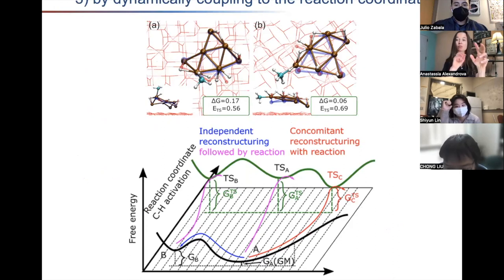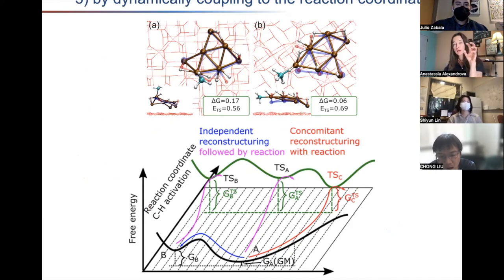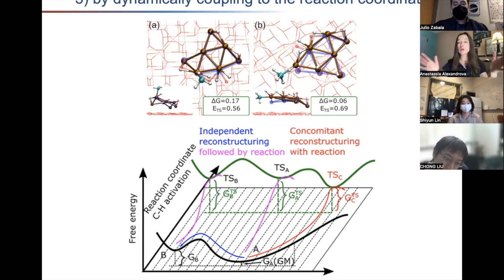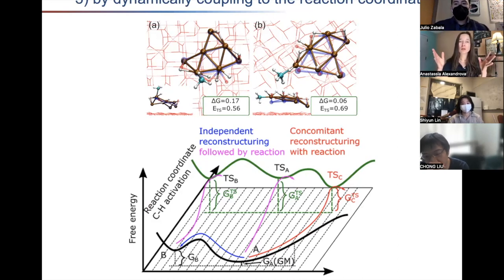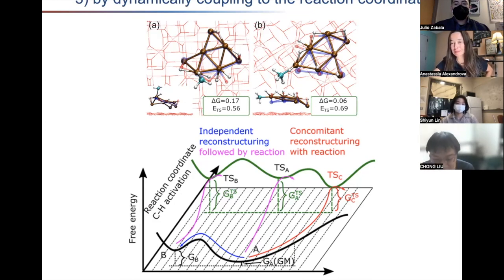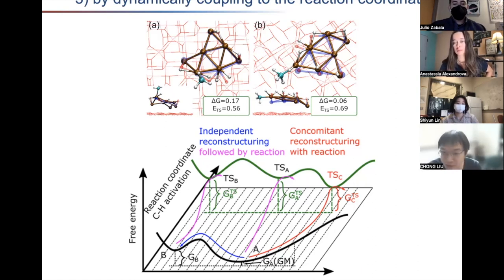We also have one paper showing that reorganization of the catalyst can be coupled to the reaction coordinate directly — meaning the reaction coordinate says not just C-H bond stretching but C-H bond stretching plus platinum is doing stuff simultaneously. That's a very difficult reaction coordinate to discover because normal NEB strategies wouldn't get you there. We fix the reaction at the transition state and sample the cluster under it, find a separate ensemble, connect forward and backward, and find low-energy reaction profiles involving platinum reorganization. Through all three ways, when we assume Boltzmann we agree with experiment better.